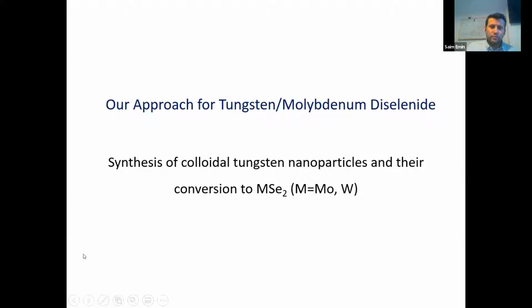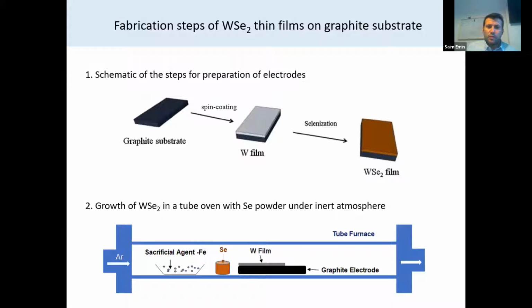Okay, next slide. The next is about tungsten diselenide and molybdenum diselenide. The same particles which we synthesized earlier, we coated on graphite substrates and did selenization. Selenization was done in a tube furnace where we also put selenium shots in a separate cup. After heat treatment, selenium melts and vaporizes, and the vapors go to the tungsten film, and in this way it grew tungsten diselenide films, and we also used molybdenum.